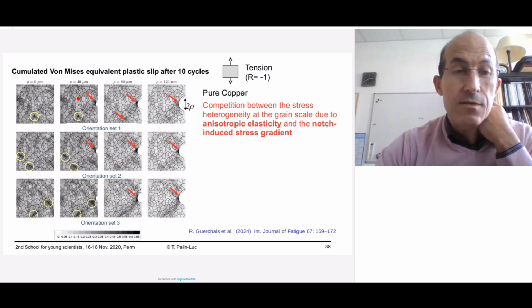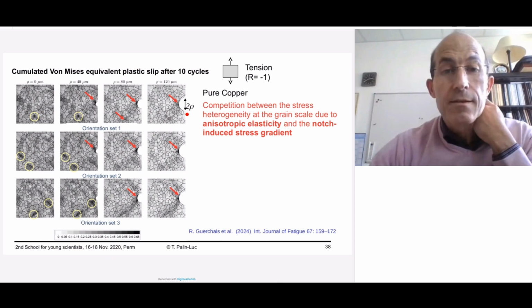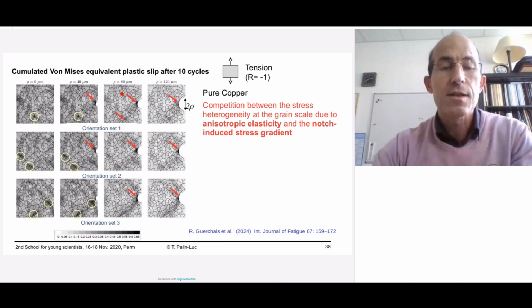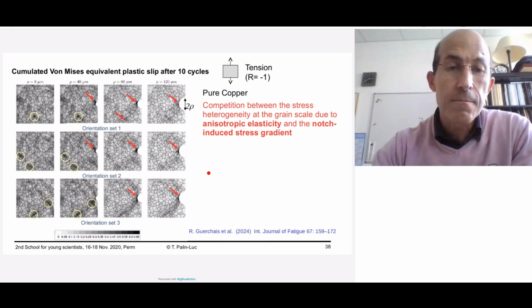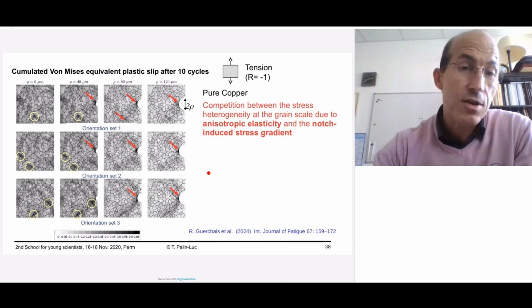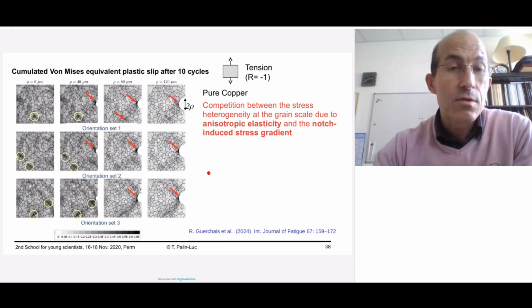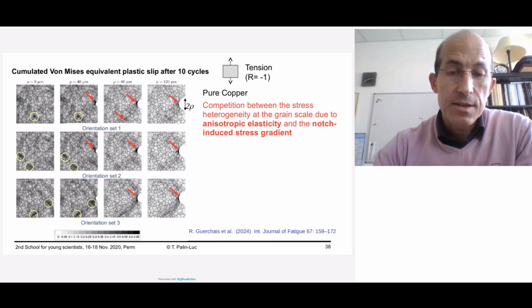So it means whatever the crystal orientation in the material, when the defect is large enough, there is localization of plasticity close to this defect. So this is very important because this simulation explains why a small striation can be negligible compared to a large notch, which is governing the crack initiation in high cycle fatigue.